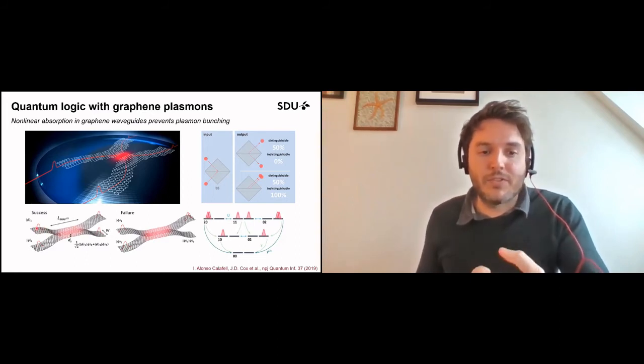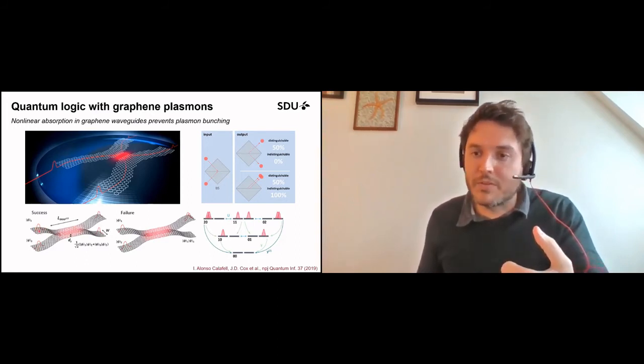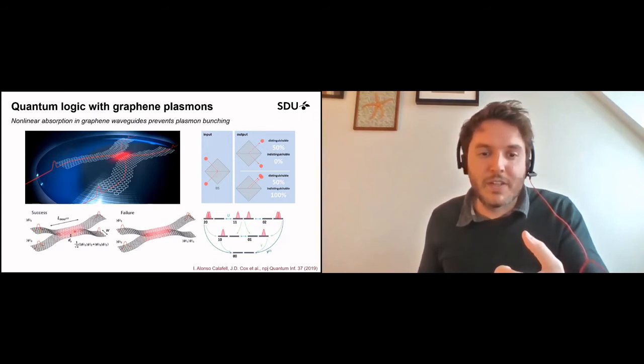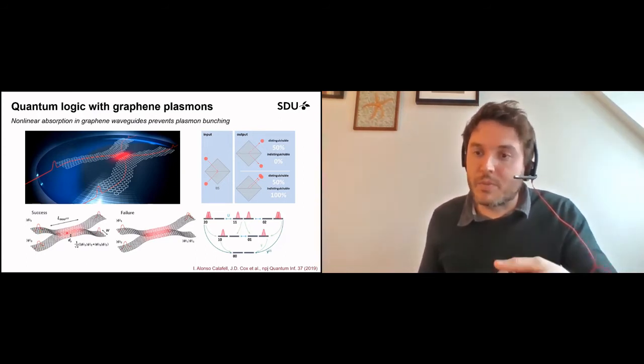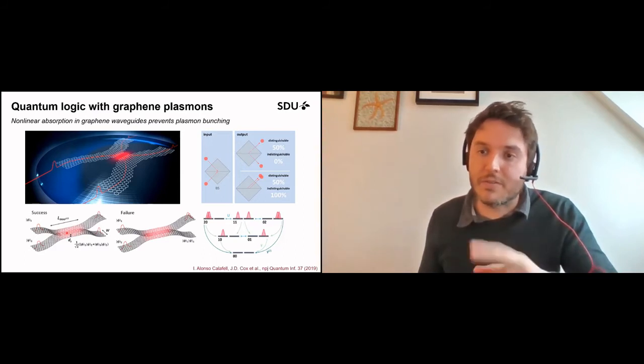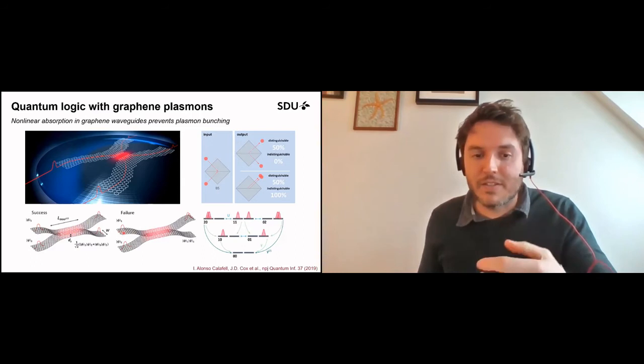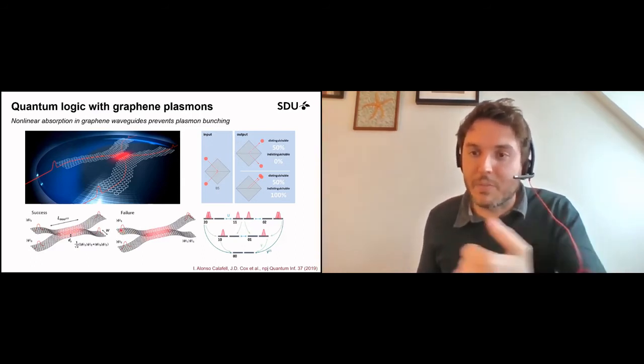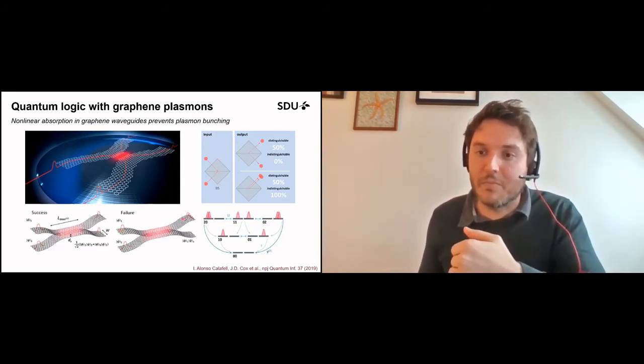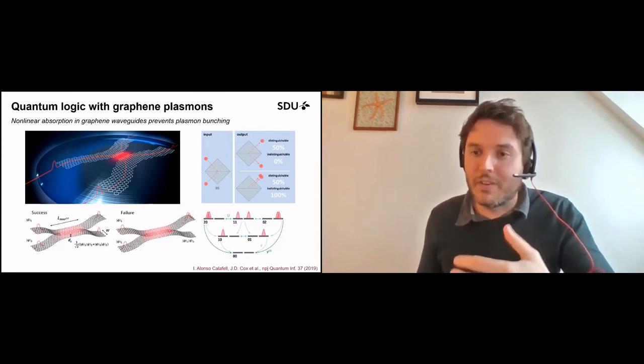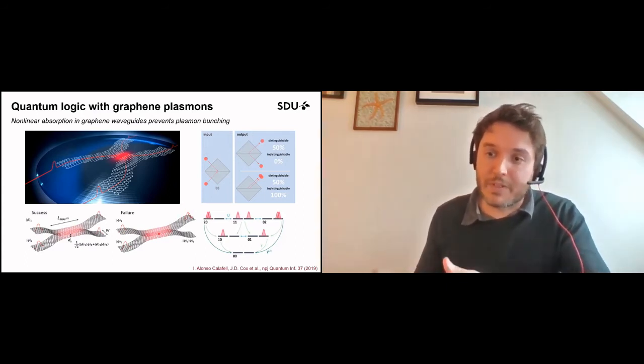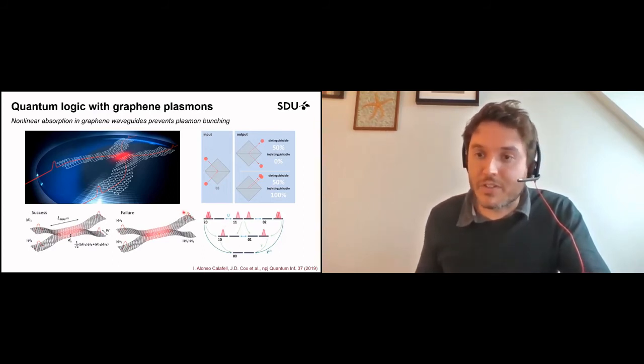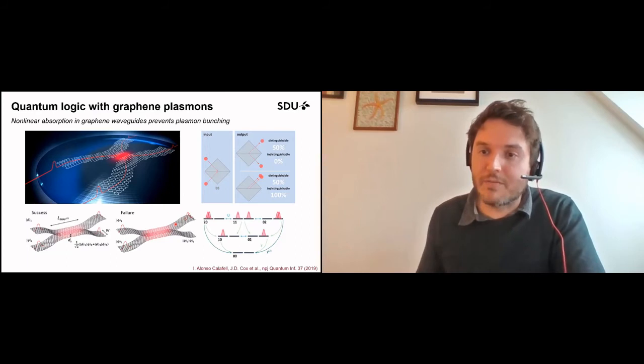Effectively, if you have two plasmons coming into the input nodes of this device, you want to have a situation where there's a superposition of them being swapped and not swapped. So going across the gate or not. The issue is that in this configuration, you normally get the plasmons bunching. So they'll always exit on the same waveguide. And we want that not to happen. So if the two plasmon absorption is stronger than the single plasmon absorption, this won't happen just by construction. And effectively, you can use that for certain quantum information protocols.